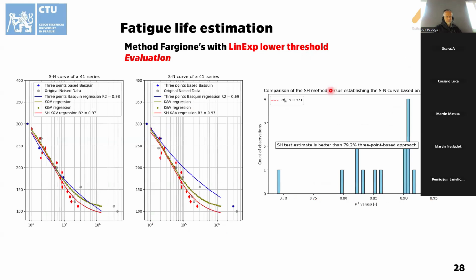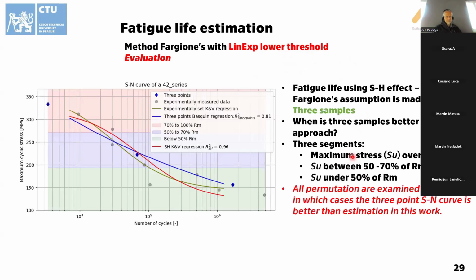With this approach, we can find out, basically, here you can see the best option for the 3 points, and here you can see the worst option for the 3 points method. And in nearly all of the cases, we are getting better results using the methodology presented in this presentation. For the 41 series, it is nearly 80%. For the 42nd series, you can see a few of the outliers, which may cause a huge problem for the 3-point regression, are working in our favor in this case.